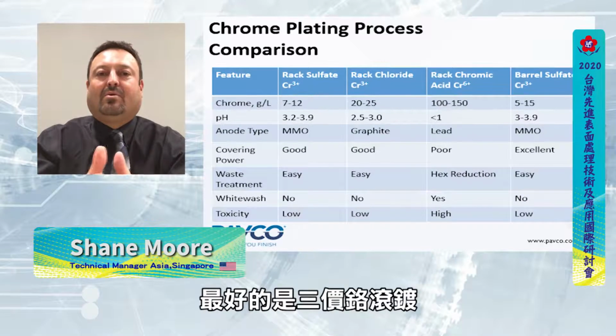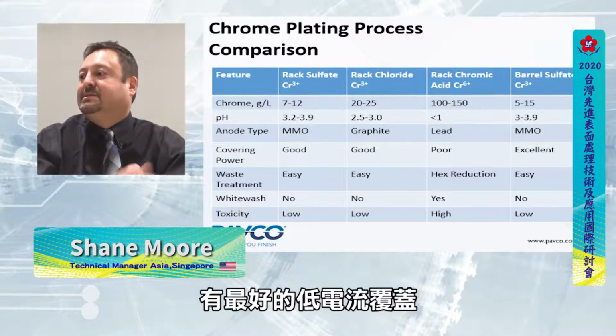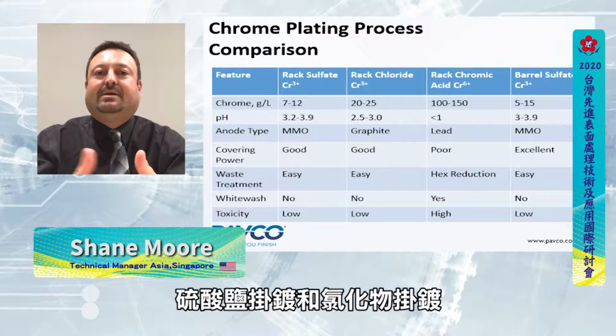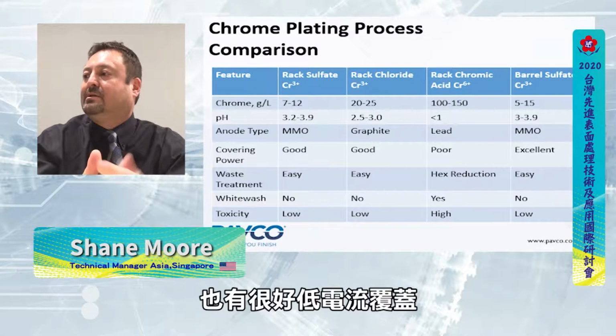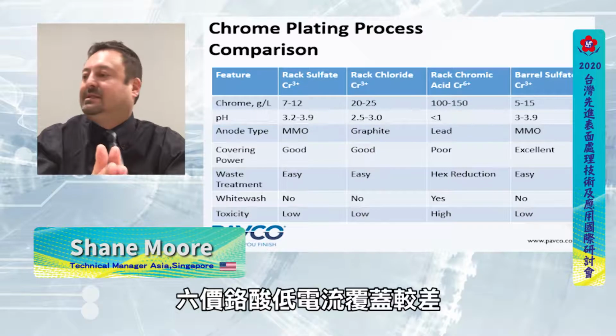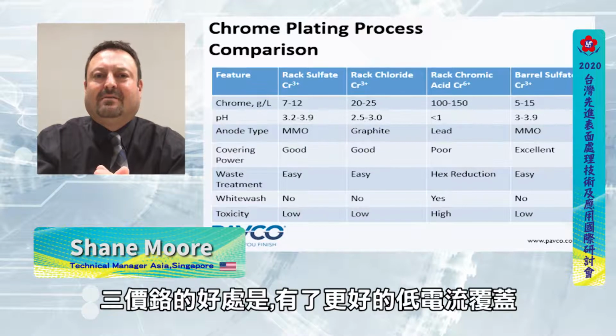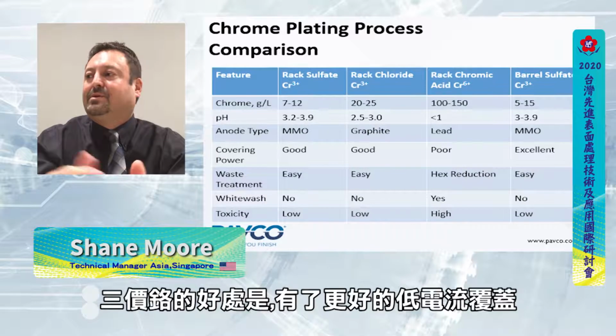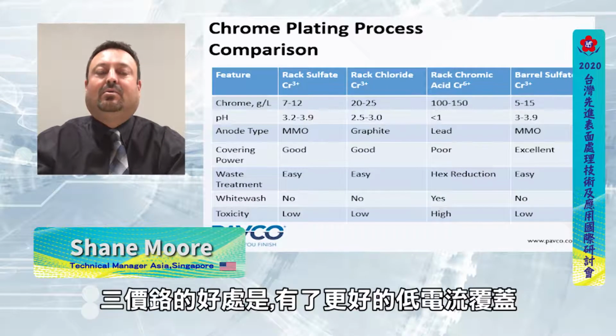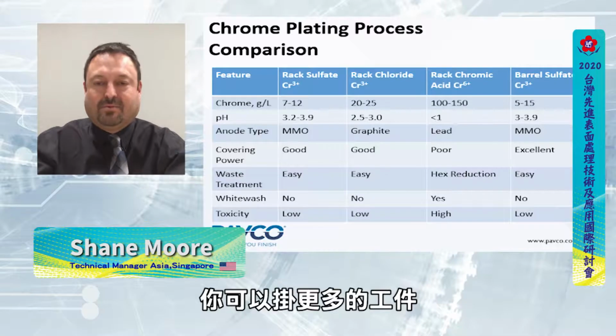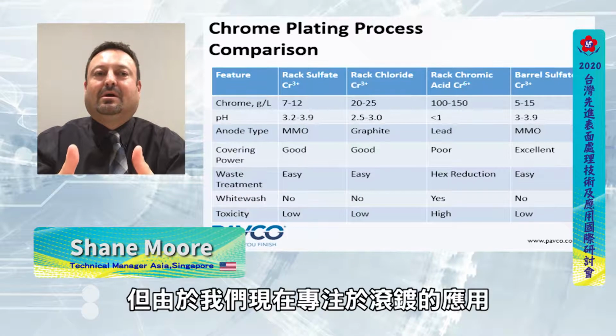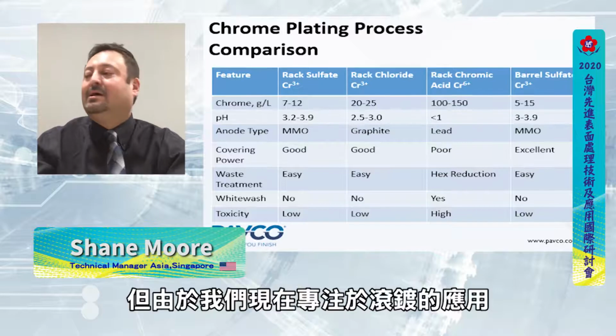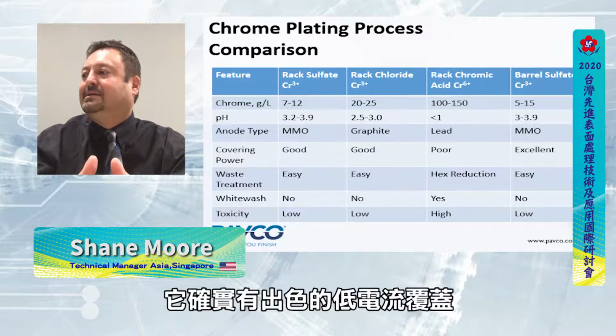As far as the covering power, the best is the trivalent chromium barrel application. It has the best low current density coverage. Rack sulfate and rack chloride have good coverage as well. Chromic acid doesn't throw down into the low current density very well. So the good thing about trivalent chromium is that with a better coverage, you can have more parts on the rack. Since we're mainly focusing on the barrel application, we'll stay with that. And it does have excellent low current density coverage.